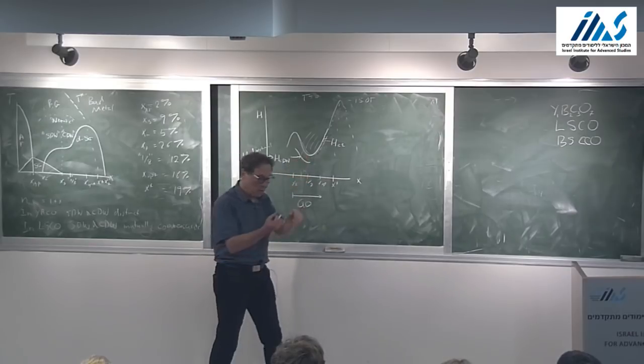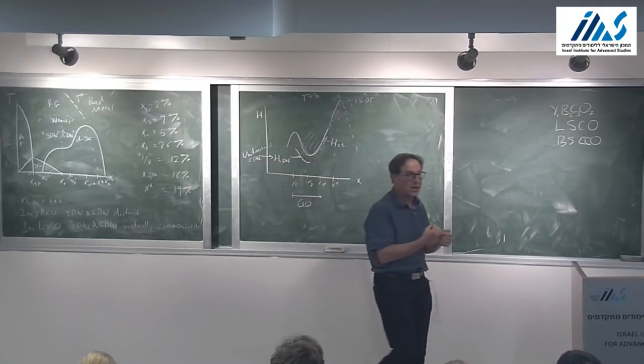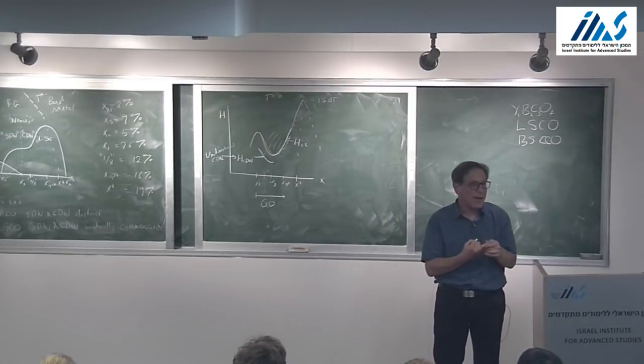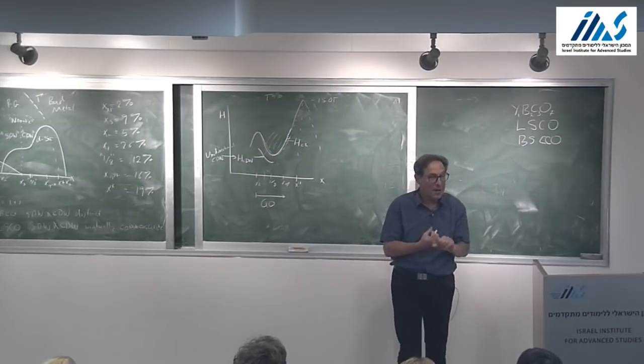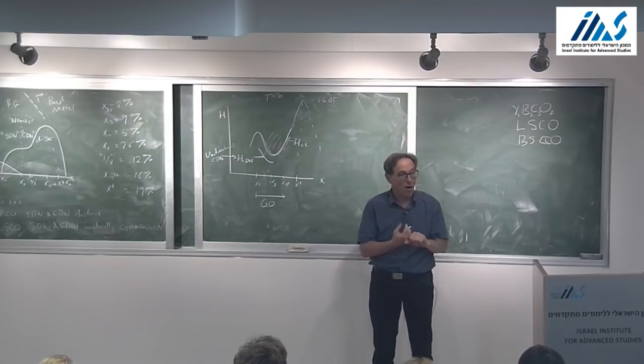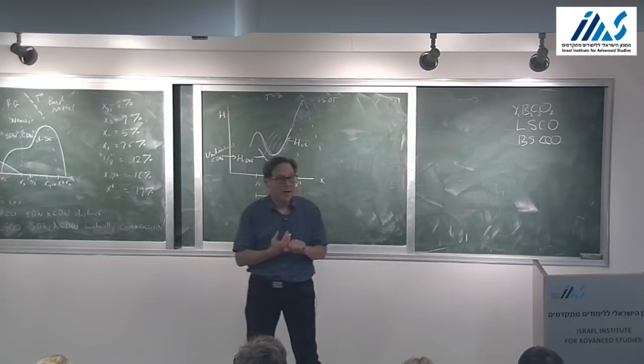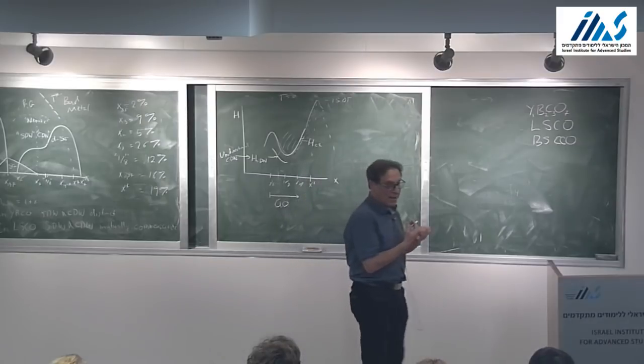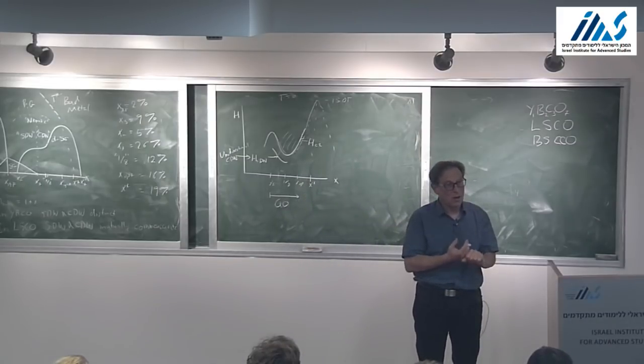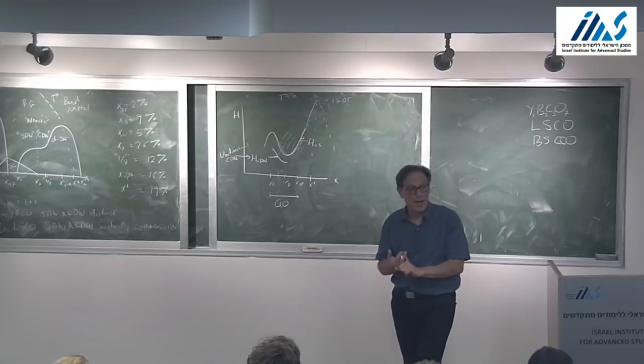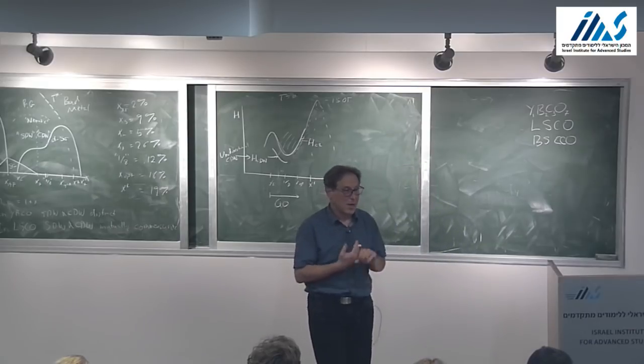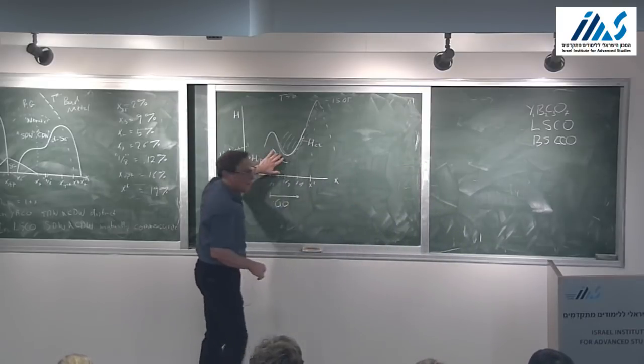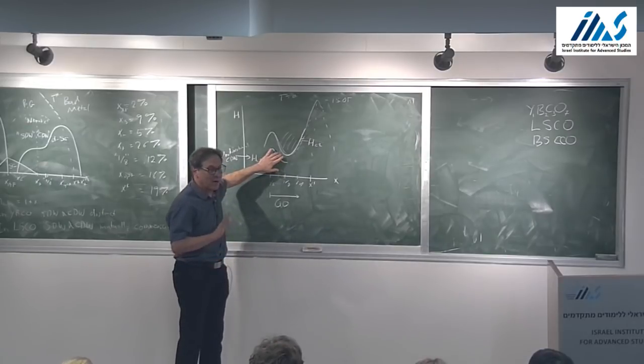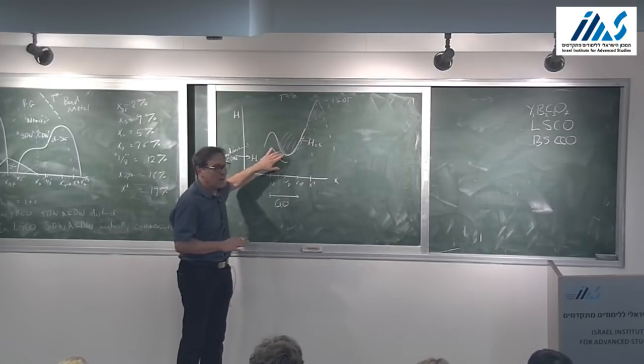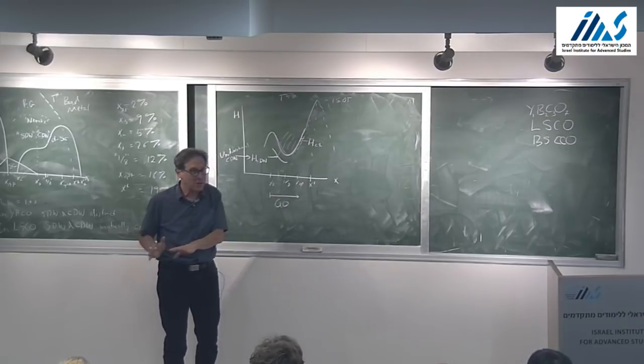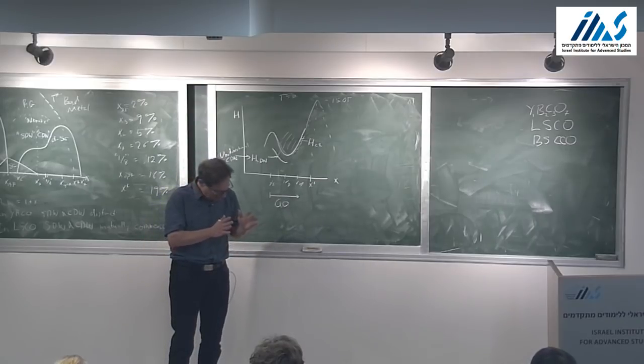Why do I say that? Well, first place, they measure a finite charge density wave correlation length, but second place, we have a general theorem based on the Imry-Ma argument that we can't have long-range order of an incommensurate density wave, of any breaking of a continuous symmetry. So the fact that there's no long-range charge density wave order here is both empirically understood and theoretically understood.